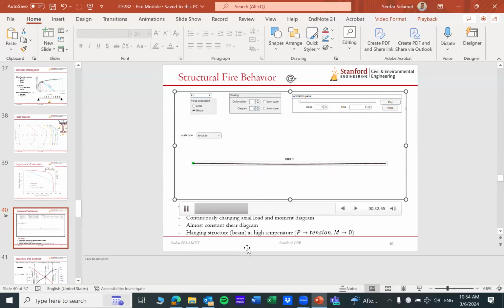And you can see here it starts with a very large compression, and that compression force goes to zero, and then you get some tension in the beam. That's interesting, right? It's quite counterintuitive if you think about it. You're heating the beam, but the vertical deflections are so excessive that the thermal elongation cannot catch up. So you're developing catenary action in the beam, into tension. So you're still in the heating.